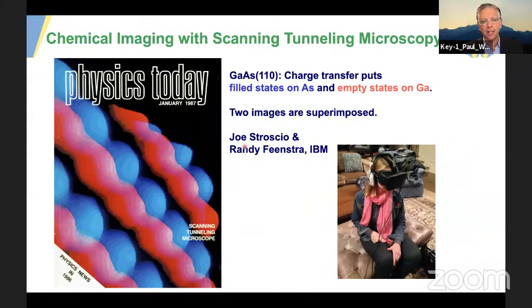So to me, the most important STM image ever recorded was actually a pair recorded together of the same area, by Joe Stroscio and Randy Feenstra. They looked at the stoichiometric gallium arsenide 110 surface, in which the charge is transferred from the gallium to the more electronegative arsenic, so that all the filled states sit on the arsenic and all the empty states sit on the gallium. And we realized from these data and others that followed that we could put on goggles, essentially, with the scanning tunneling microscope when we did these spectroscopic measurements and look at the molecular orbitals, which are the basis of chemistry. They're also the basis of the transport.